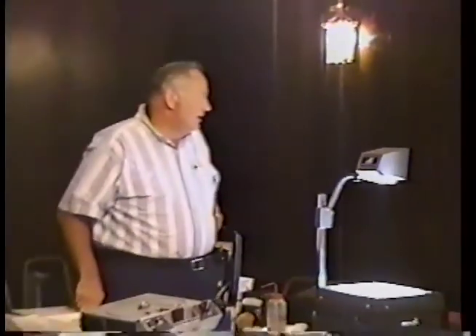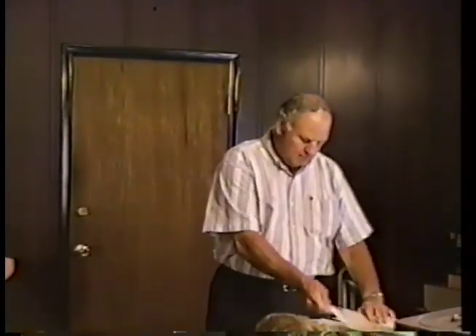Okay. And you guys deal in hours, but it's a long time. 1.5 million miles in certain applications is 4 years. In some others, 5, 6 years, and in a short line railroad, then you're looking at 15 to 20 years. So this Super finish here is a 30 to 40 RMS, and our specs call for a 20 to 30 RMS. That's really smooth. That's our spec. Yeah, that's relatively smooth. It doesn't deal with the percentage of porosity that you want within there.